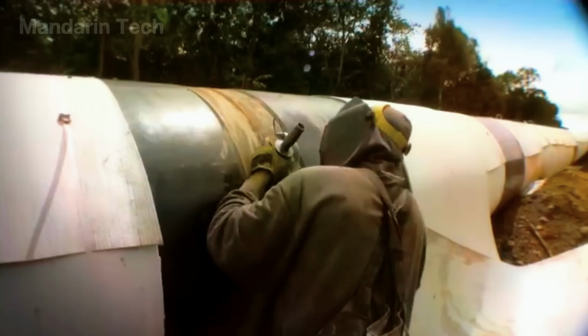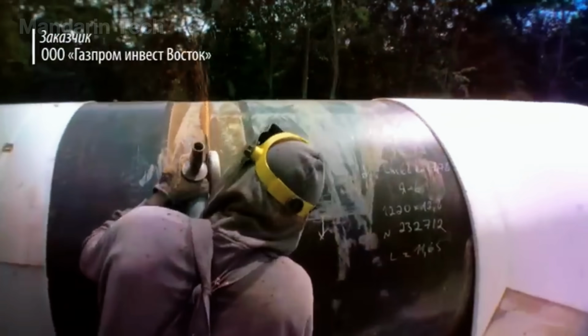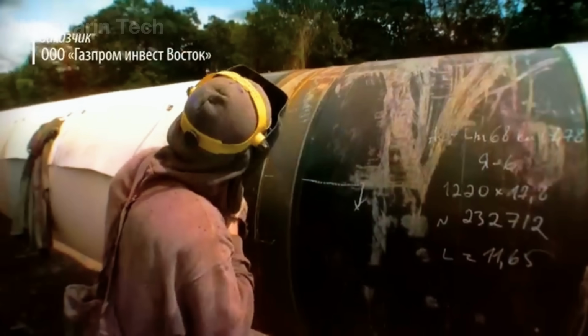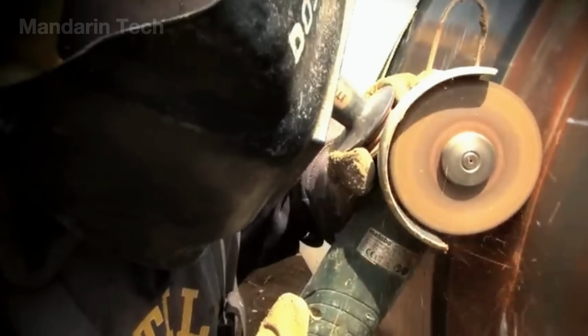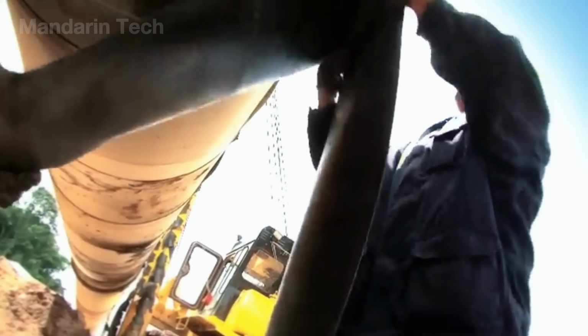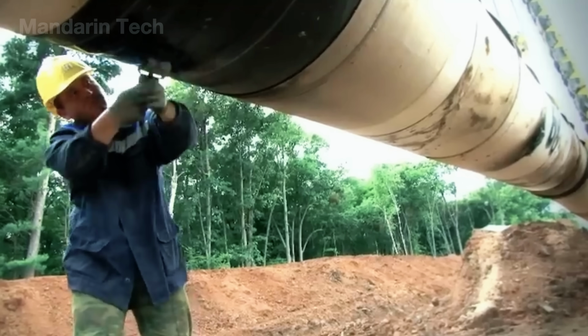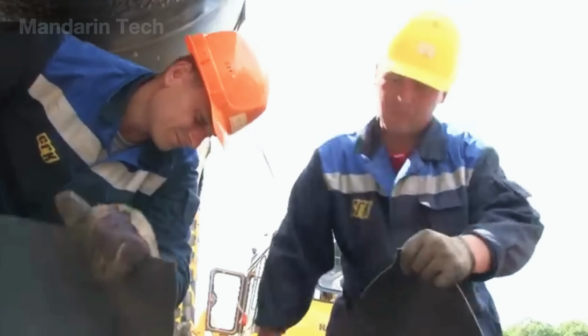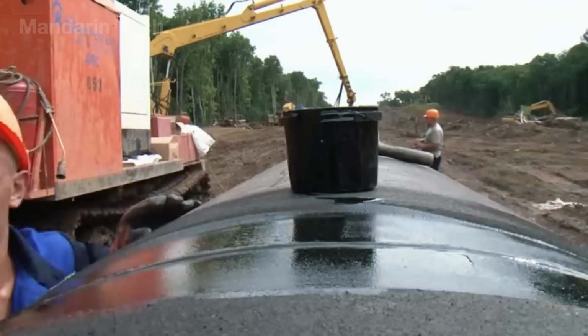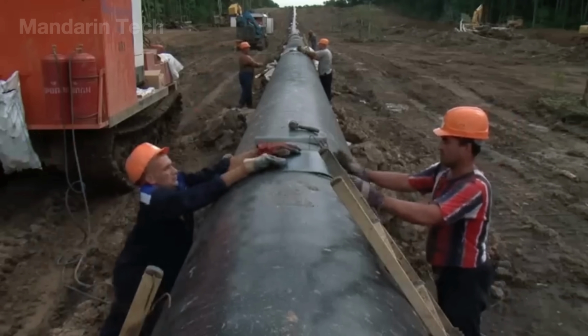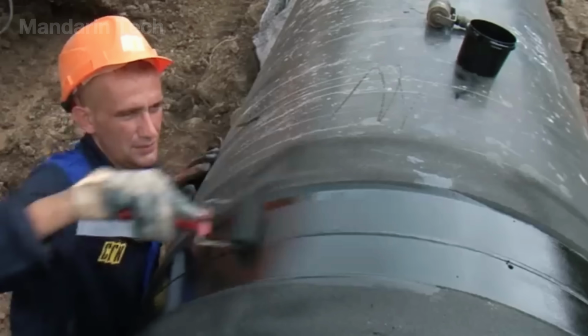The welded joints along the pipeline section are inspected using self-propelled X-ray inspection equipment. If any defects that do not meet the required standards are detected, the joints are repaired immediately on site. Once the joints pass inspection, the construction teams proceed to apply protective coating to the pipe section. To protect the pipeline from rocky ground conditions, the outer surface of the pipe is wrapped with an additional protective layer known as a rock shield coating.